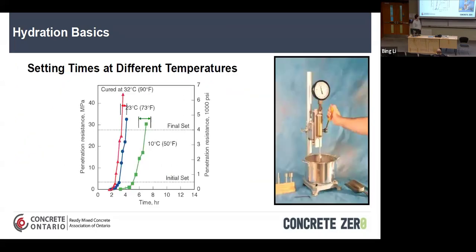So you can see set time differences depending on the temperature. If the concrete temperature is 32 degrees Celsius, you'll see two things happen. First, the initial set happens sooner than a typical concrete at 23 degrees Celsius. And then the other thing you'll see is that initial and final set are relatively close together. When it comes down to colder temperature concretes, initial set is slower. Final set and initial set difference in this case, for example, is 2 hours. In this case here, it's about a half an hour. And the initial set here might be about an hour, for example.